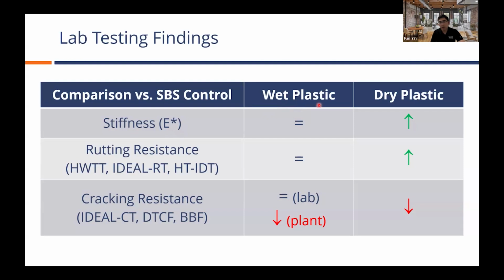If you look at the wet plastic mix, pretty much we were able to match the engineering properties of the SBS, which is really not very surprising to us because, as I mentioned, we did our homework up front to engineer the binder formulation to make sure it's going to perform. So this is a very important finding: it's not something where we should expect to just drop in recycled plastic and hope that it's going to work. As engineers, we really need to engineer the formulation for the wet process. And the result definitely is showing the promising outcome that we expected.